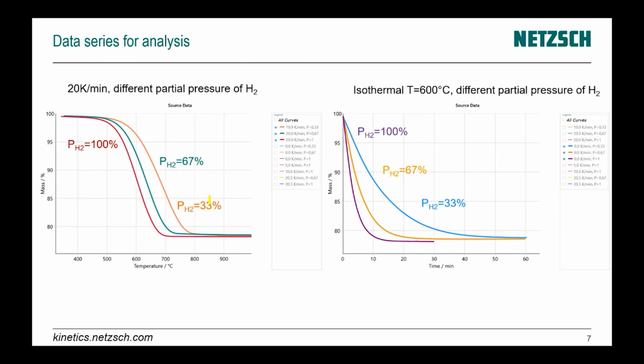Let's start. Here we have our measurements. We have two sets of measurements. The first one is measured always at the same heating rate, 20 K per minute, with different partial pressures of hydrogen. The slowest one has the lowest value of the partial pressure of hydrogen, here 33%. The next one is 67%. It is faster, and the next one is pure hydrogen, 100%.